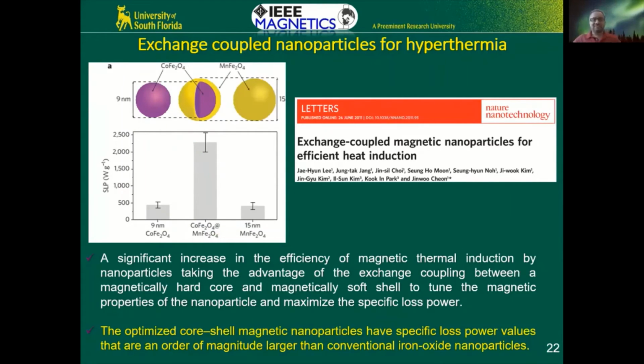Okay, so I thought, well, that goes against my idea. We tried to see if we could do this, but then I looked at the materials and saw the first element, cobalt. Cobalt is poison. It's impossible for the FDA to give you an approval for cobalt-based materials. So the best chance of getting through the system, getting FDA approval and going for clinical trials, is to make sure that we work with biocompatible oxides that are already approved by the FDA. So we have to make a core shell particle based on Fe3O4, but all oxide, okay?